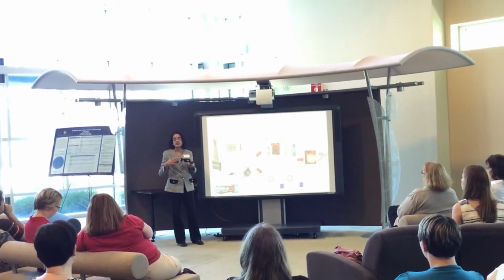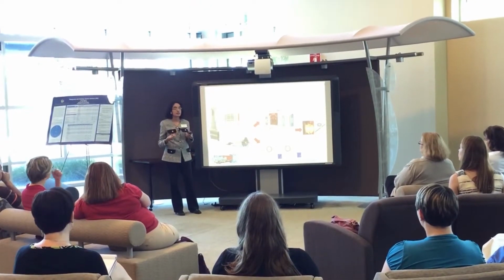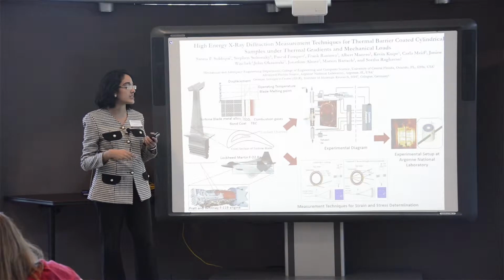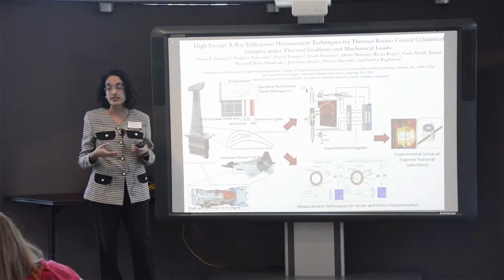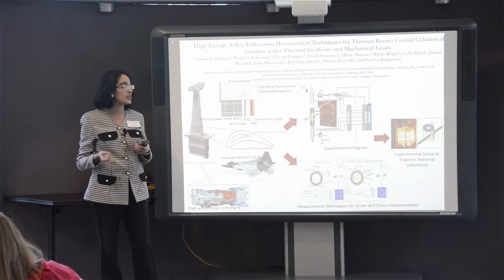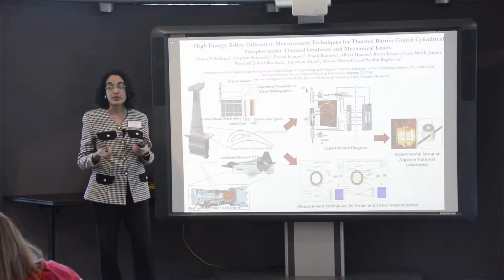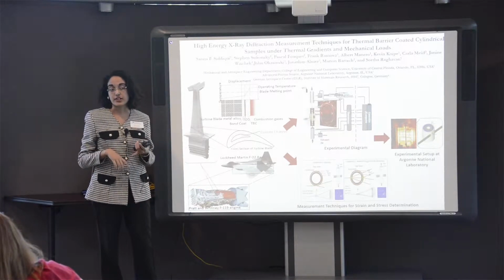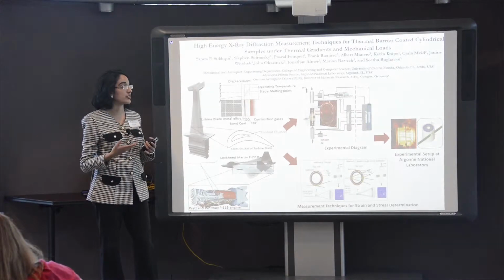Under realistic turbine operational conditions in flight, because of the large thermal expansion mismatch in these layers, you have the development of large residual stress within these layers, and that has been linked to the initiation of failure mechanisms of the coating itself. So our study, which was a collaborative effort between the DLR German Aerospace Center, Argonne National Laboratory,